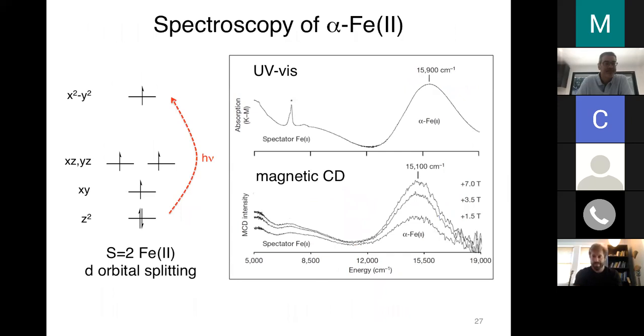Okay, so the way we got to this answer, very briefly, is that you can look at the UV-Vis spectroscopy of these ion exchange zeolites, and by looking at how the UV-Vis spectra respond to different levels of iron loading, you can figure out which features correspond to spectator iron and which correspond to the active alpha iron site. In this way, we correlated this UV-Vis feature at 15,900 wave numbers with the active alpha iron site.